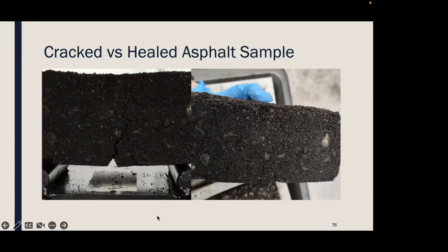Okay. Now, looking at this, we have actually taken some samples. We've actually induced a crack. Okay, and then let it self-heal and come back and measure how well it's actually healed. And you can see that the gap actually has healed again. Okay, and then of course we've gone and applied some tests to see, firstly, whether the crack has continued to propagate. No, it didn't propagate. And we've seen some healing whereby after cracking, it's actually healed. So that's a good thing.